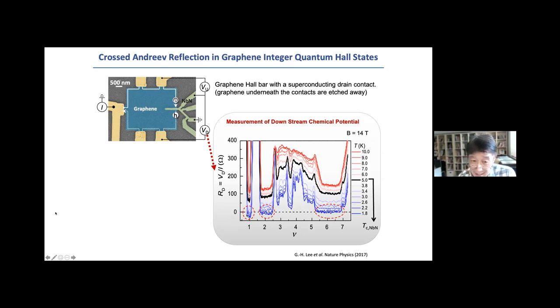You see that the signal is not necessarily big. Even at ν equal to 1, we get about 50 ohms of resistance, where we're supposed to get about 25 kilo-ohm. It's very small, about 1% or a few percent of the signal. But clearly that negative signal is well beyond our detection limits, indicating that indeed we can make the cross-Andreev reflection across this thin superconductor.